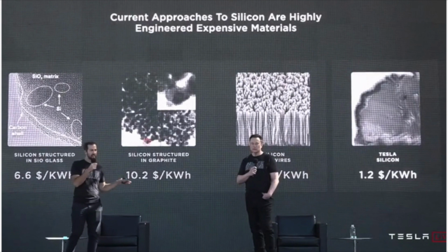Another really fascinating thing for me and for everybody was that the anode design they showcased yesterday is like $1.2 per kilowatt hour. That's amazing compared to everything else. If you look at what is in Tesla right now, SiOx, they do have silicon oxide in the graphite right now, and that's costing them around $6. And silicon structured in graphite, there's another category that's about $10 per kilowatt hour. Now they're almost reducing it by 10 times. That's amazing. And so I was able to go search and read a little bit more on this.